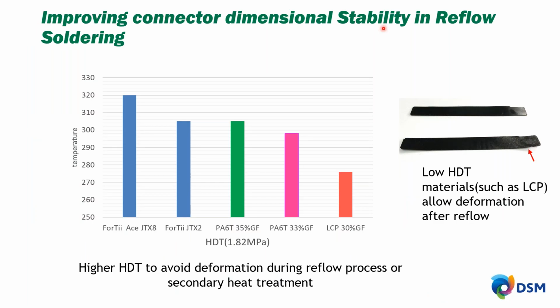The dimensional stability of our ACE JTX8 material is also quite appropriate for the reflow soldering process. It boasts low deformation at those kinds of temperatures, and one way to measure that is the heat distortion temperature. The HDT is a rating of how the material moves under load and temperature. So you can see that the ForTii Ace JTX8 boasts a 320 C rating for the HDT, as opposed to some of the other PPAs that are out there with much lesser heat resistance, and LCP even lower than that. And the issue there is if you do have loads on the part and they see that sort of temperature, they may be subject to permanent deformation or warping in the reflow soldering process.